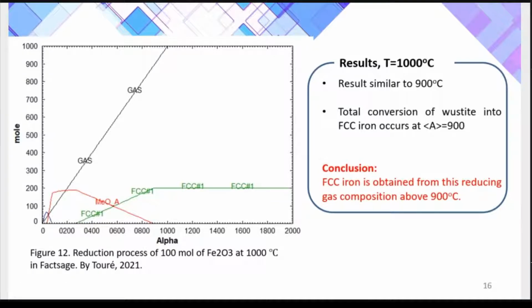At 1000 degrees, which is the operating temperature mostly used in Midrex's process, we are also able to form the FCC iron, but at a slightly lower alpha, because it's alpha equal to 900. So this experiment implies that FCC iron is obtained from this reducing gas at temperatures above 900 degrees.